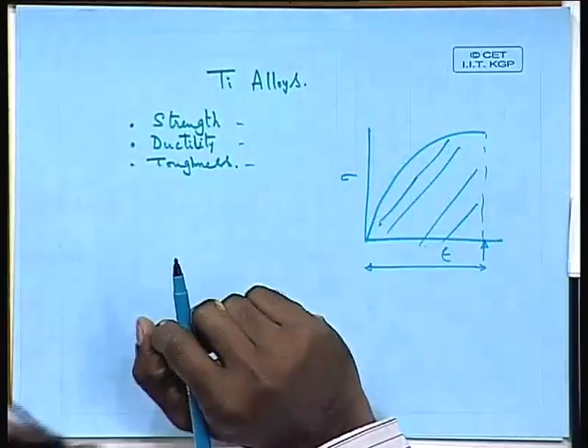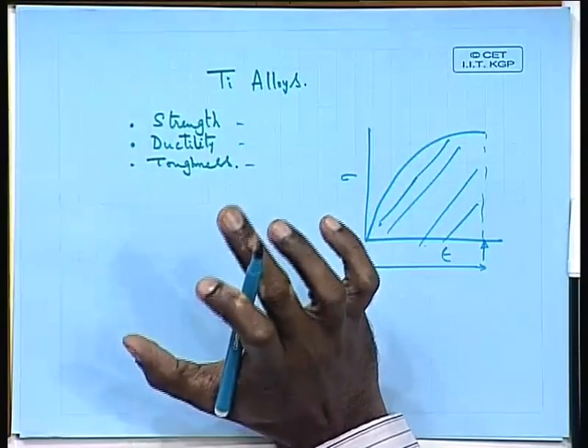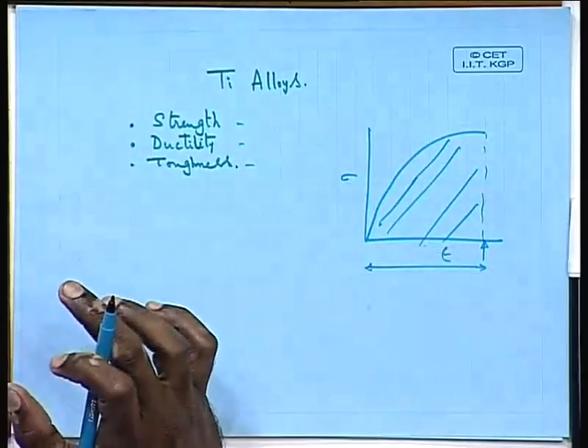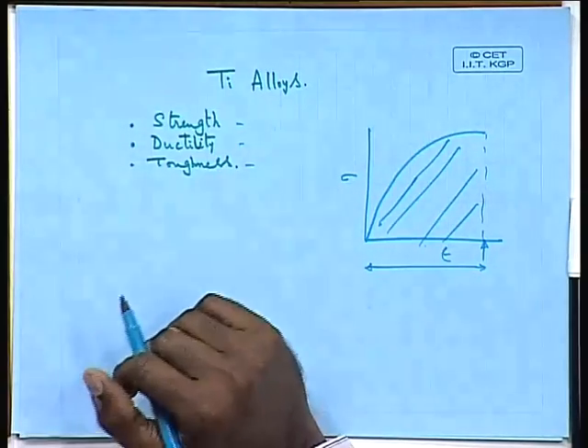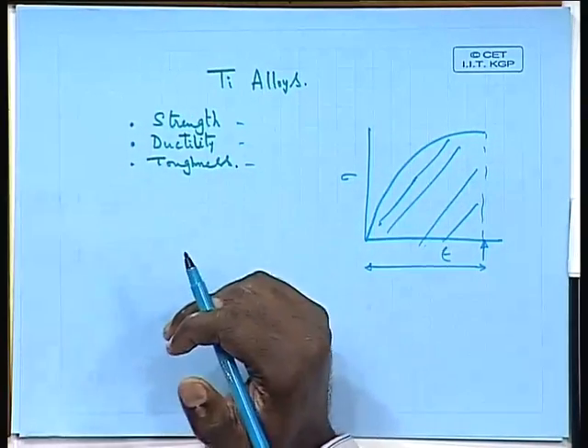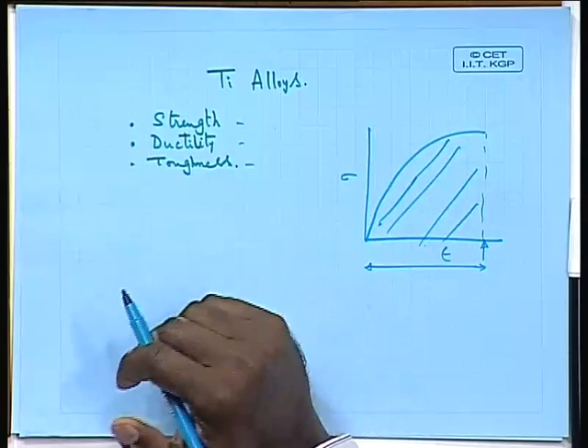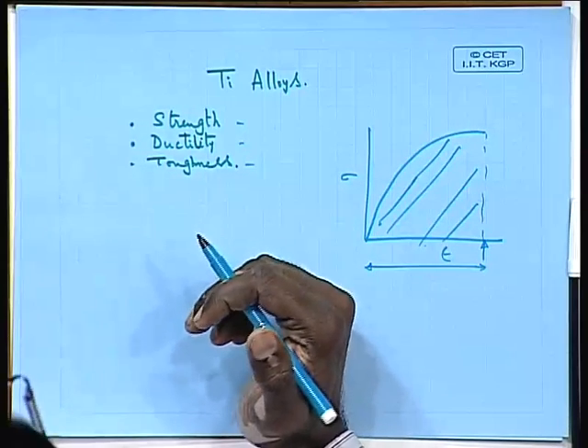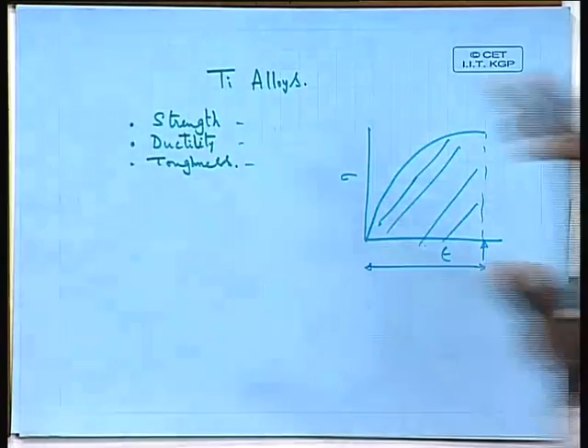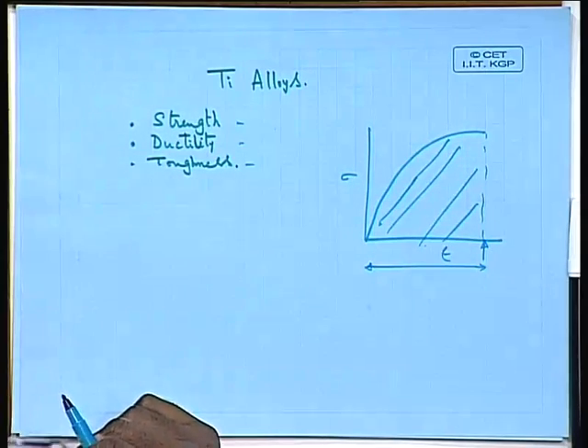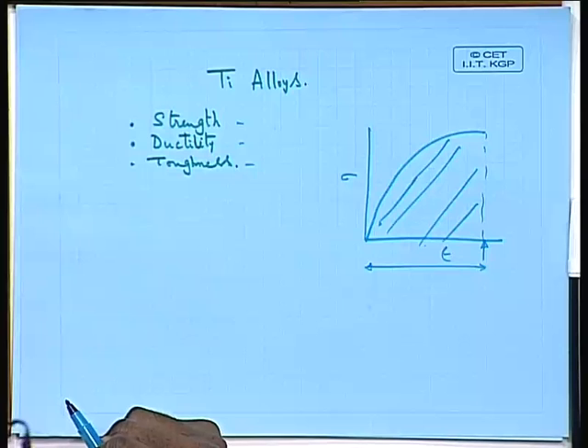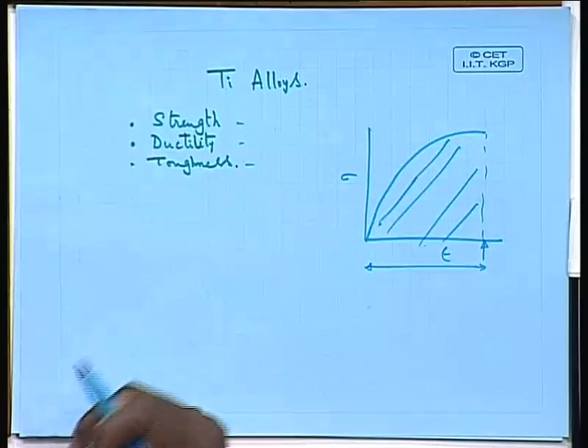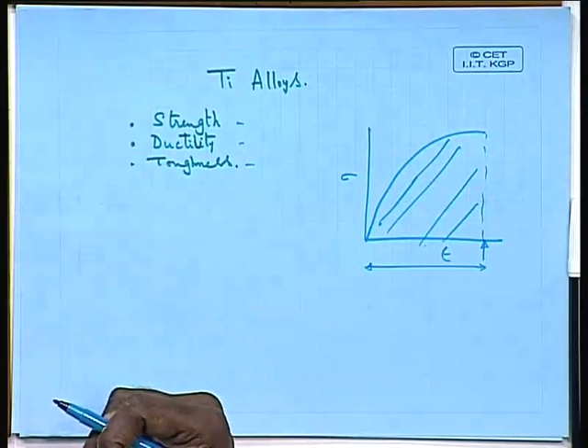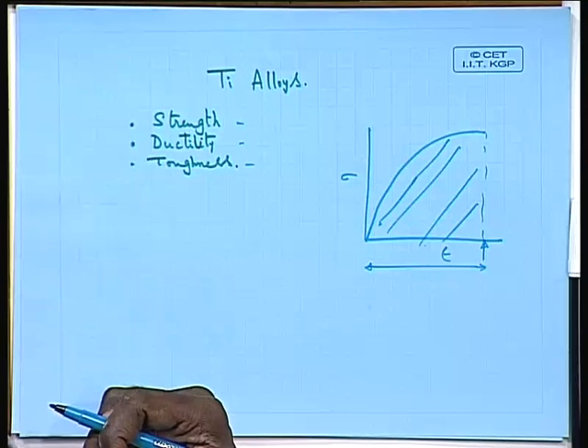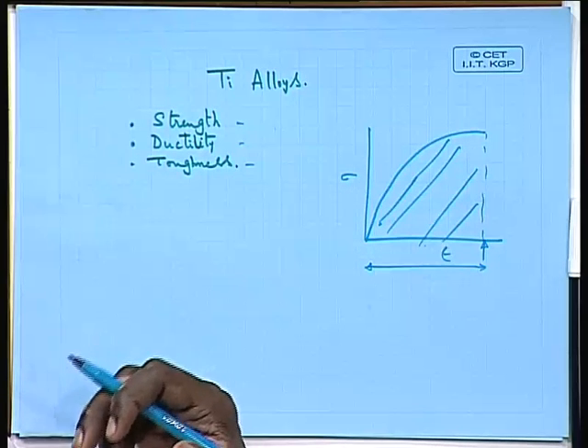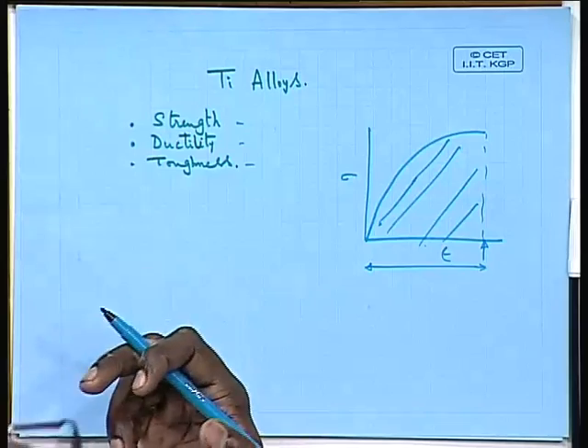So this is as far as quantitative is concerned, but qualitatively we know that the two concepts are different. One is about deformability, another is about the resistance of the material to crack propagation. That's why we say a brittle material has very poor toughness, because a crack can propagate very fast in the material, and then finally the material will break. Whereas, for example, even martensite we say is very tough under many conditions. In many alloys, martensite is very tough, though it may not be very ductile.